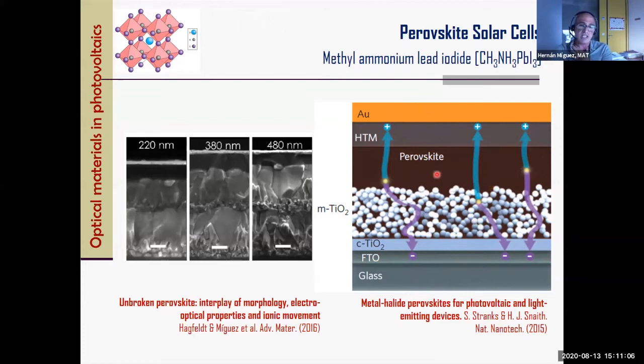One is that the perovskite is a very efficient absorber, so it's difficult to improve its absorption. But there is a drawback in this material: in the composition of the standard perovskites used in this field, there is lead, and lead always poses an environmental problem. There are a lot of regulations everywhere against the use of lead, as they are against the use of cadmium in devices, right?